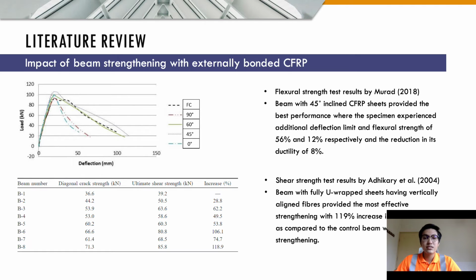strength. For the flexural strength, Murad concluded that beam with 45-degree inclined CFRP sheets provided the best performance where the specimen experienced additional deflection limit and flexural strength of 56% and 12% respectively, while the reduction in its ductility of 8%. While for the shear strength, Adhikary and Mutsuyoshi concluded that beams with fully U-wrap sheets having vertically aligned fibers provided the most effective strengthening with 119% increase in shear capacity as compared to the control beam without any strengthening. With these research paper results, it can be concluded that externally bonded CFRP provided the most in shear strength capacity of a beam.